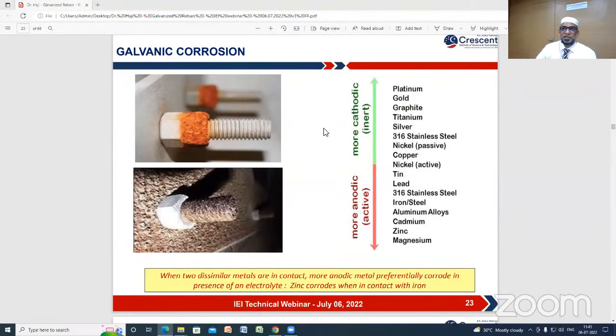Now we will try to understand the mechanism of working of this galvanized rebar. This is very, very important. According to the bimetallic corrosion theory, if you connect two dissimilar materials, the less noble material will corrode and it will protect the noble material. In this picture is the basic of the galvanization process. Here you can see these two nuts are made with different materials. The rusted one is the less noble material, and this one is the more noble material. Since we have connected these two nuts, two dissimilar materials, the less noble material corrodes, protecting the noble material.